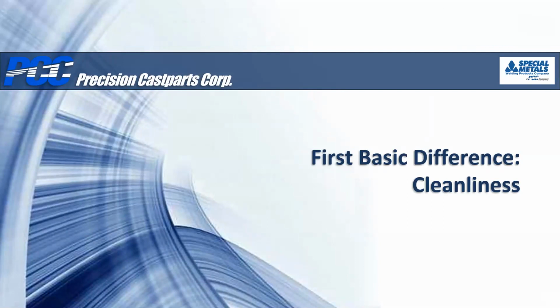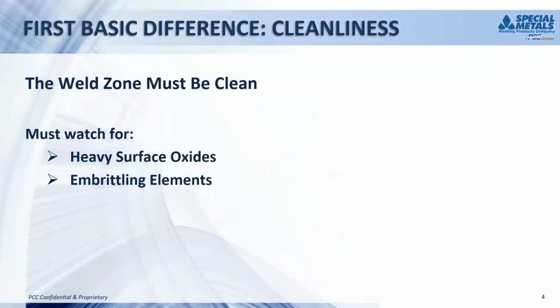So the first basic difference is cleanliness. And this comes into a really kind of a neat thing. We're going to talk later about the low penetration into nickel alloy base metals. And one of the reasons for that is the surface of the nickel alloys needs to be kept away from sulfur of all types. And so that part plays into the penetration talk that we'll be getting into later.